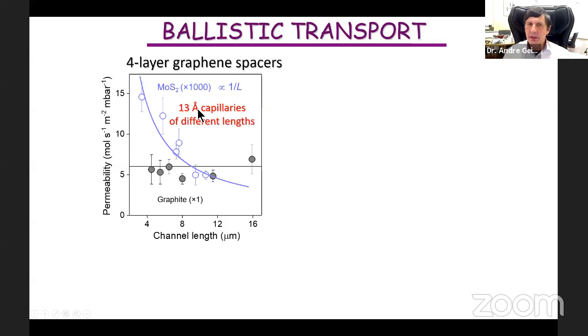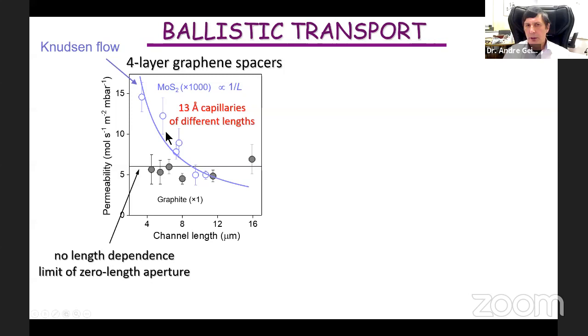What you find out is that while Knudsen flow still well explains transport of helium through molybdenum disulfide capillaries, there is essentially no dependence of the flow of helium through graphite channels on their length. It's like whether you take a very, very long channel or a very, very short channel, just an aperture, you observe the same flow. How do we understand this quite unusual observation?